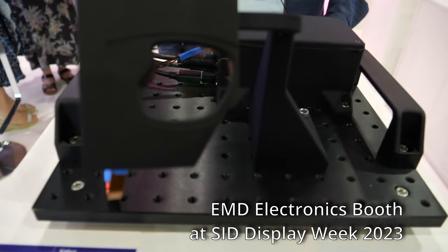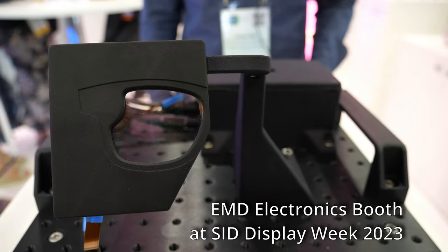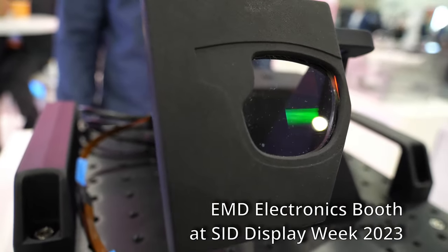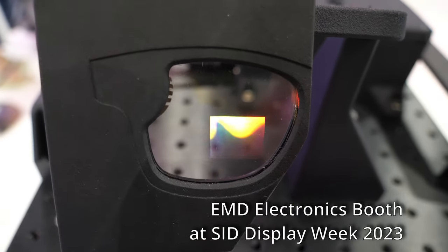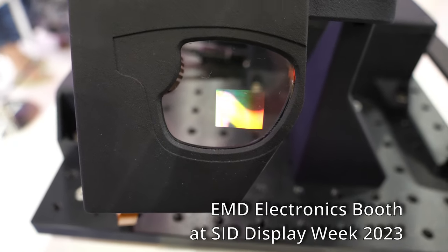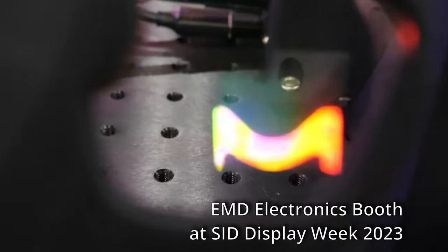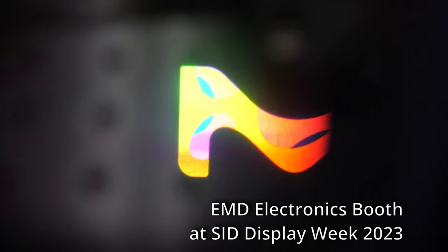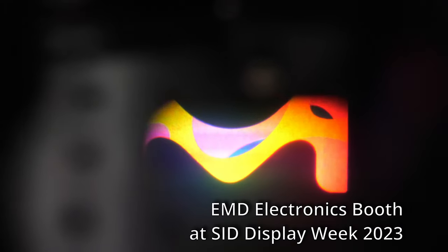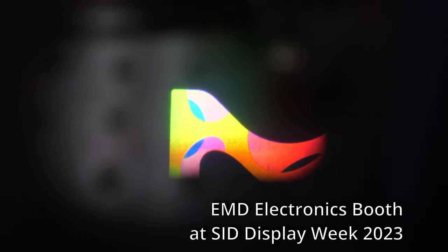So what do we see right here? What we're looking at here is a full colour waveguide using polarisation volume holographic technology. It utilises a layer of glass, on top of that a photosensitive alignment layer, and then on top of that a layer of liquid crystal which is then polymerised to give a solid film. That can be used to create diffraction gratings or diffraction lenses. What we're offering really is the materials to enable this technology.